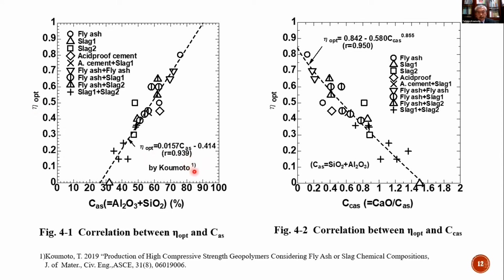In the present lecture, I propose newly to use a factor Ccas, which is equal to CaO over Al2O3 plus SiO2, considering the three main factors in this factor. And the present factor was correlated with ηopt, and could obtain the ηopt equation and higher correlation factor R equal 0.950, shown in figure 4.2.